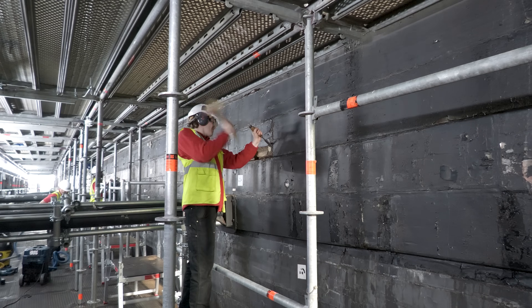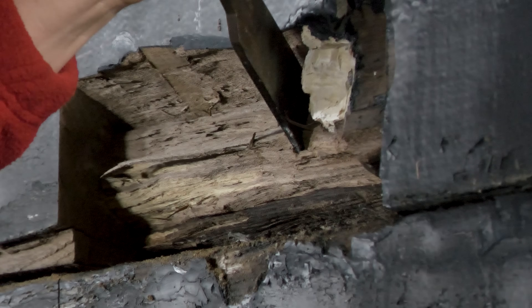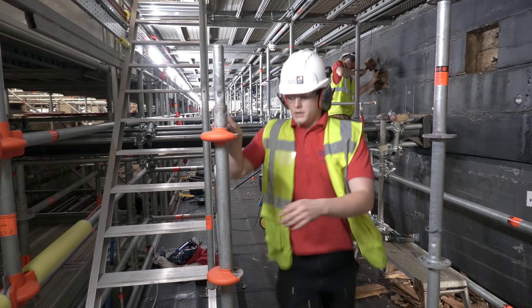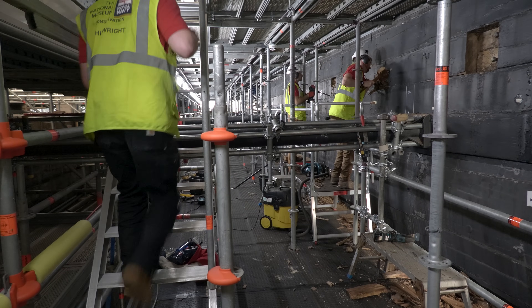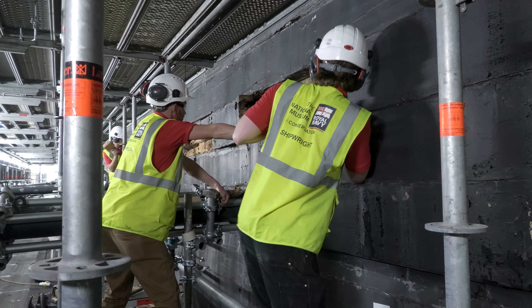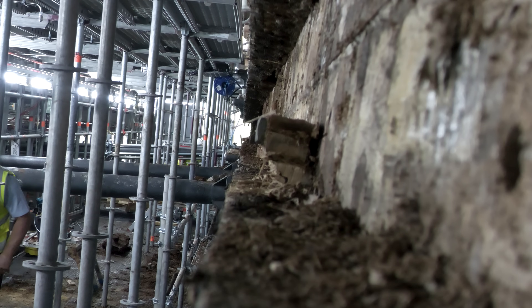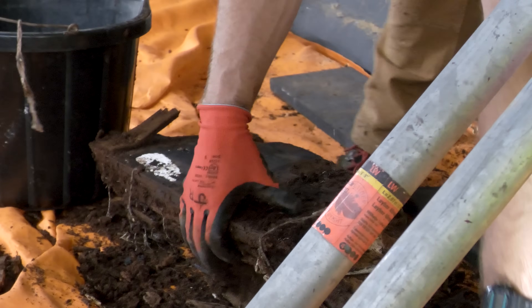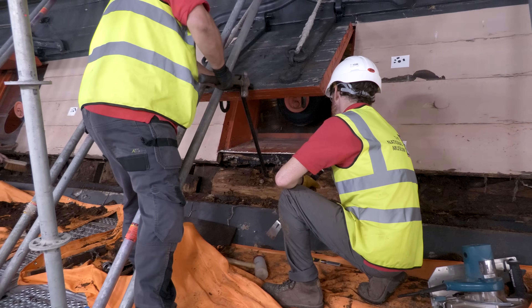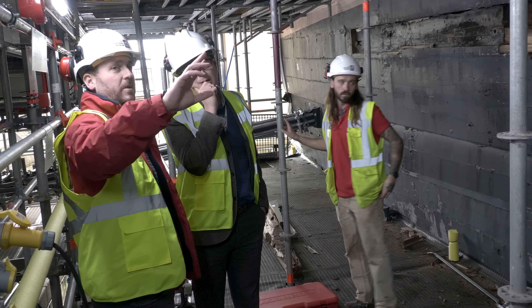The replanking is affecting the ship from the waterline up to the top of the hull — these are the areas where the weather affects both planking and internal frames due to the exposure of rainwater and the summer heat. The planks were removed carefully, avoiding any further damage to the internal frames. The majority of the strip planking cannot be saved due to the extent of the decay and delamination of layers used in the construction, meaning all these elements need to be rebuilt.